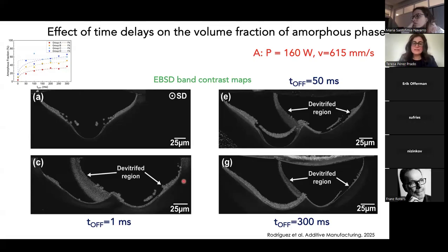So what we did was, okay, let's go back to basics. Let us choose some conditions within group A, which are here. And then let us take an amorphous substrate and just print one single laser track. And these are EBSD band contrast maps. So here black is amorphous, and these gray tones are the crystalline region. So this is a cross-section. The scanning direction goes inside the screen. So this is a cross-section of this first pass of the laser.